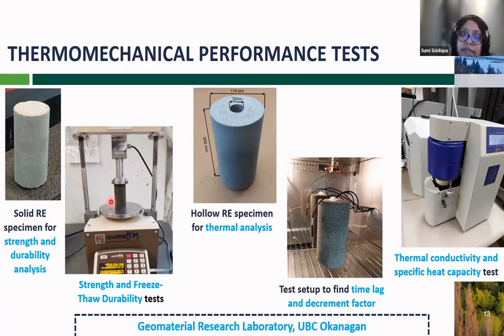So this is the solid rammed earth specimen for strength and durability analysis. We looked into the durability and strength analysis and also the freeze-thaw analysis of this material over a period of time. Then we used this hollow rammed earth specimen for thermal analysis, using the environmental chamber for time lag and decrement factor with this sample, and also the thermal conductivity apparatus for the thermal conductivity and specific heat capacity.